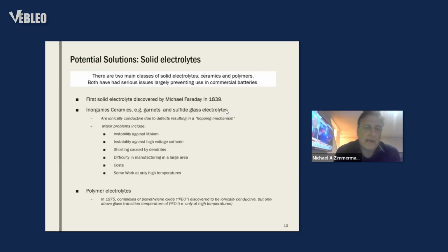Some things like sulfide glass have difficulty in being stable against high voltage cathodes. Then people put coatings onto the cathodes to minimize that. Shorting is continuously a major issue, which is dendrites from lithium metal going through the separator. And that's a major defect, which can lead to thermal runaway and other events.